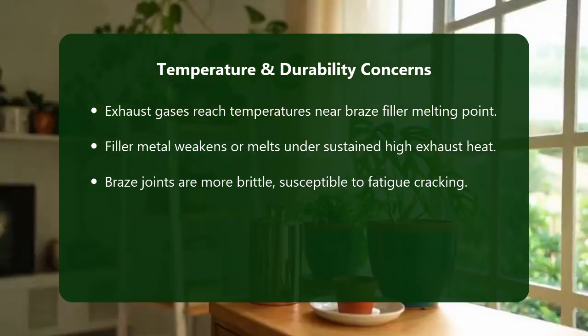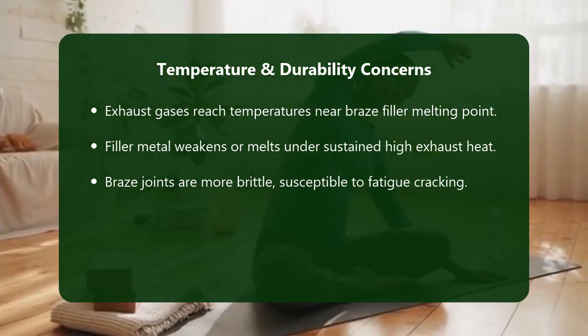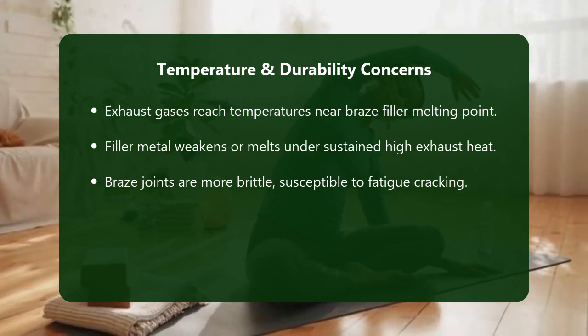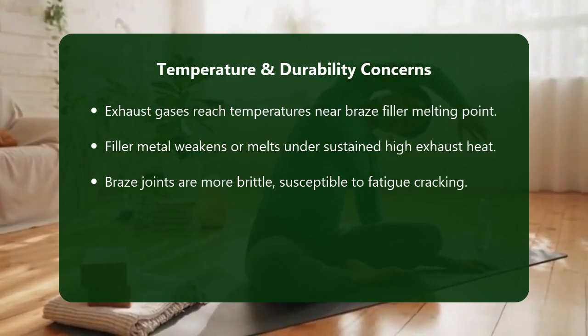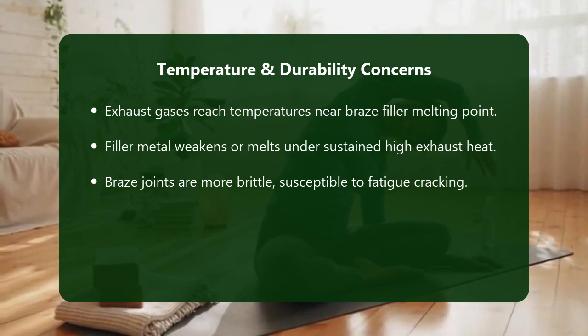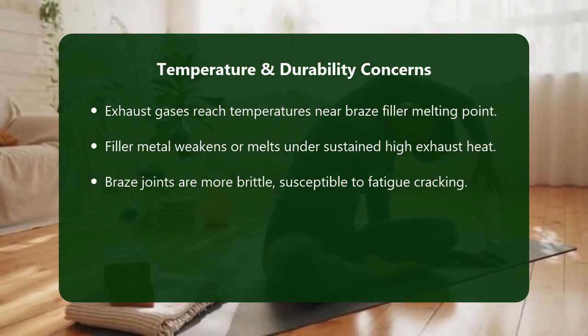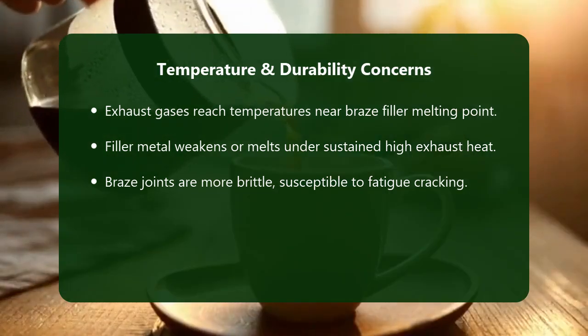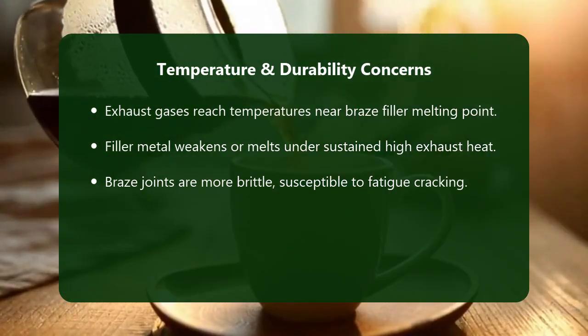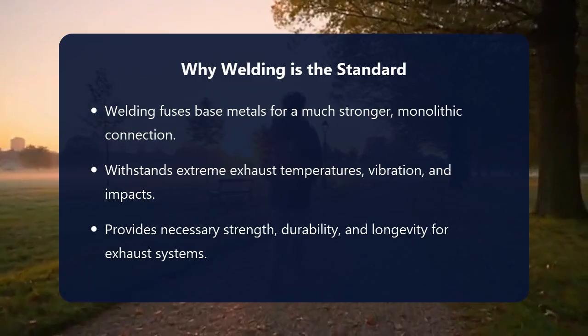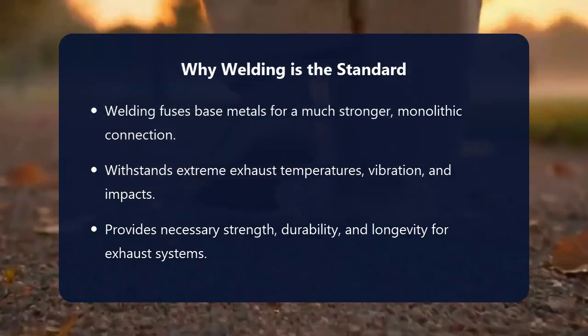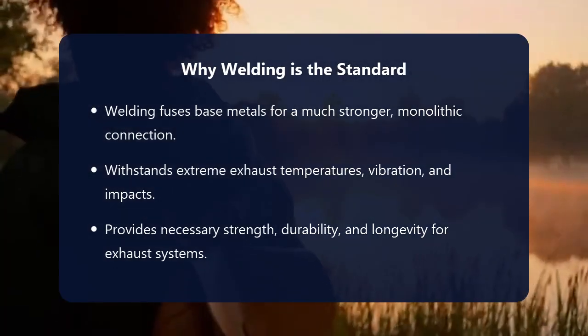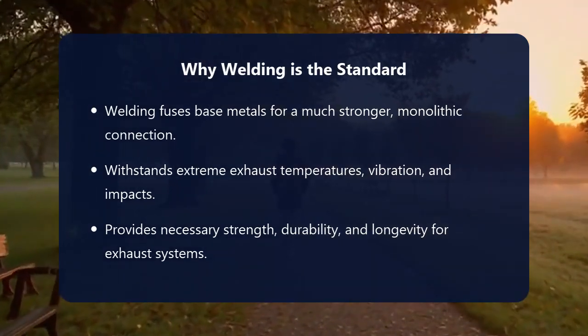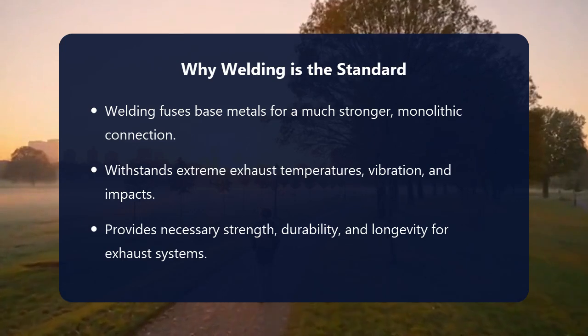Furthermore, the ductility and fatigue resistance of a braze joint are often inferior to a properly executed weld. Exhaust systems flex and move, and a more brittle braze joint is far more susceptible to cracking and failure from repeated stress cycles. Corrosion resistance is also a consideration. The filler metal might react differently to the corrosive environment inside and outside the exhaust pipe than the base steel, potentially accelerating degradation of the joint.